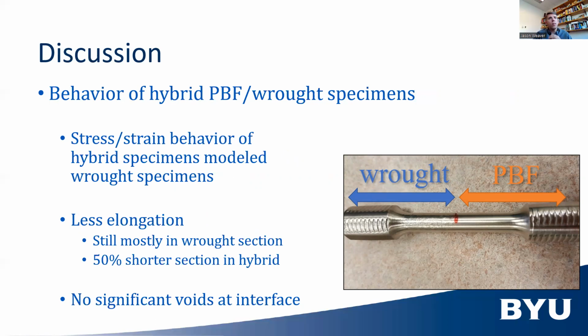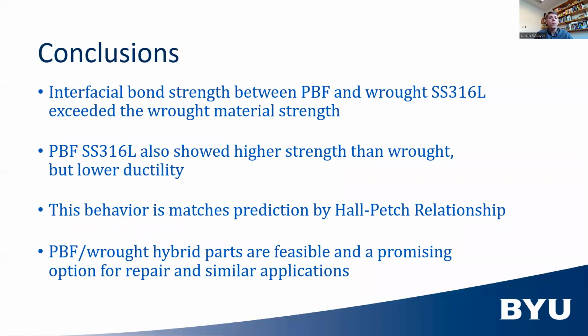And as we saw in the charts, the stress and strain behavior of these hybrid specimens was very similar to what we found in the wrought specimens. And that makes sense if most of the deformation is occurring in the wrought area, not at the interface or the powder bed fusion part. We did see less elongation in these samples, and that makes sense if this elongation is still happening in the wrought section, but because the wrought material is only half of each sample, we have a lot less material to play with and to elongate before failure. And then as we saw before in the microscopy, we didn't find any significant voids in the interface, which is also very good for the application.